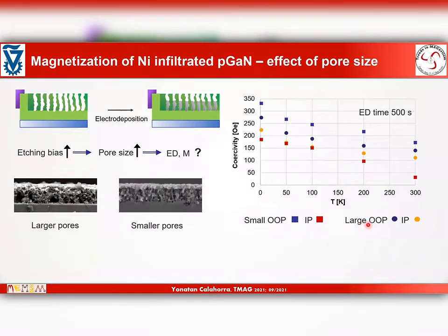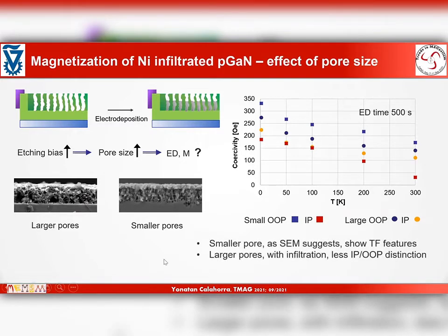And this distinction between in-plane and out-of-plane is dramatically reduced for the larger pores with nickel embedded inside. It makes some sense, right? It's no longer a thin film. So what about the effect of the deposition duration in the larger pores now, in samples where nickel is more